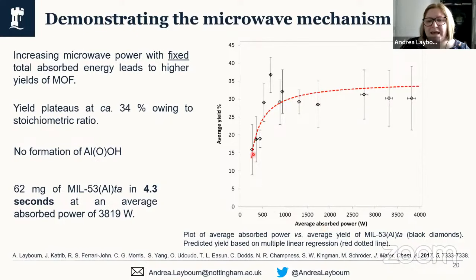We can see that we get a rough trend where, as the power increases, the percentage yield of this material increases, which is indicative of this selective heating mechanism. Now, you probably will notice that the yield is quite low, particularly for a MOF synthesis, and particularly for this MOF, at around 34%.